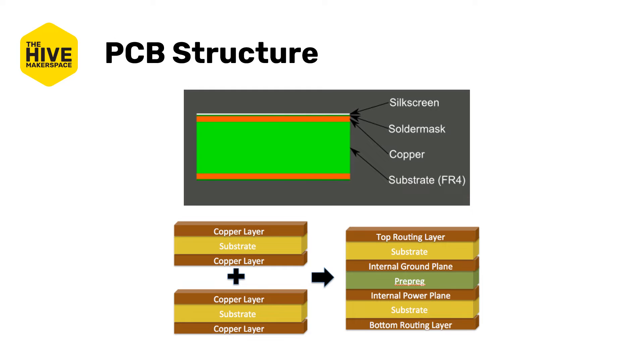The thickness of this metal can vary. In the US it's generally described by ounces per square foot, and you'll most commonly find quarter ounce, half ounce, one ounce, and two ounce weights, though others are possible. Internationally these would be described in microns, with half ounce copper equating to roughly 18 microns and full ounce copper equating to roughly 35 microns.